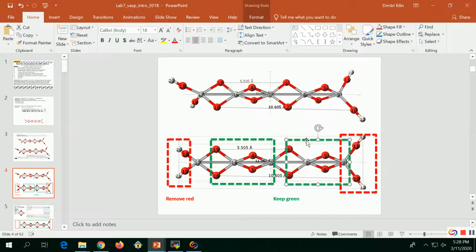Yes? What's your meaning of putting some vacuum? So we need to bond these two monomers, or repeating it together, or there is no actual bonds. In electronic structure calculations, there are no actual bonds, but there is a distance between atoms. If I define the size of the unit cell, it should be not the distance from this oxygen to this titanium, but the distance from this oxygen to this oxygen. So some amount of empty space must be included into the unit cell. Okay? And one needs to do special effort to take it into account.